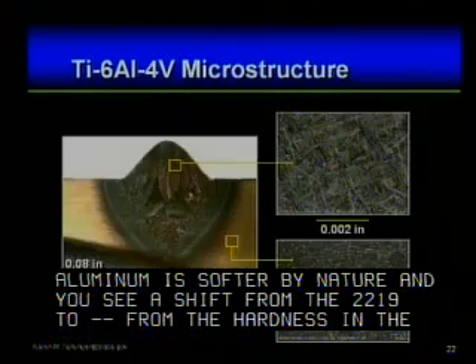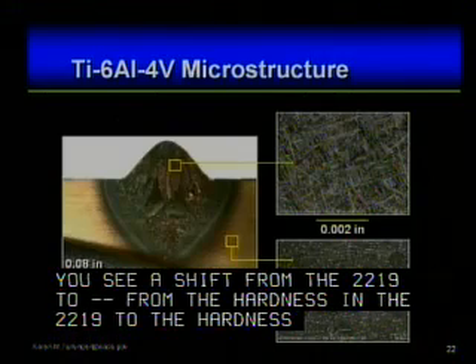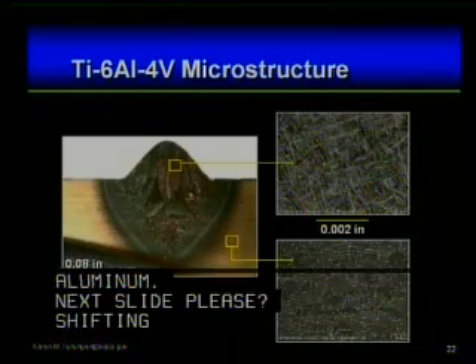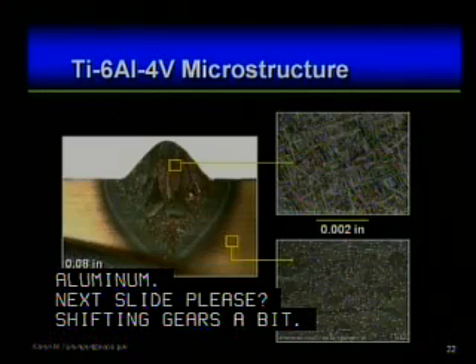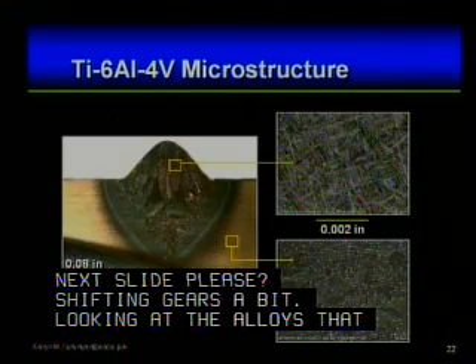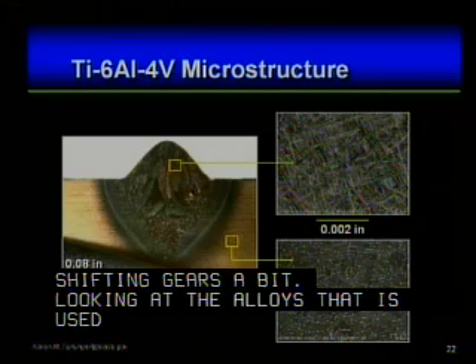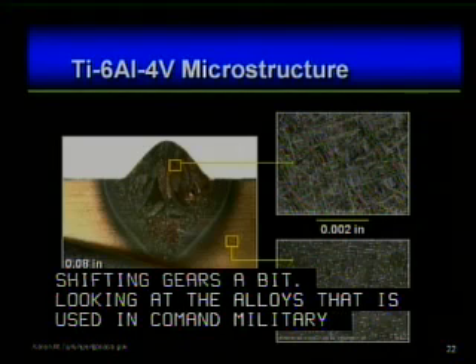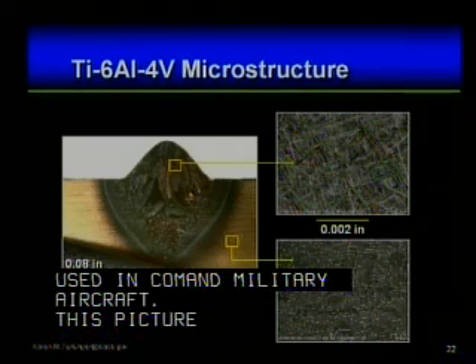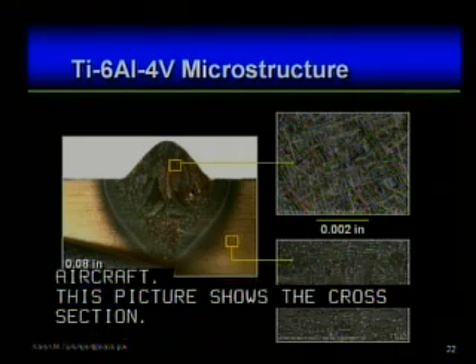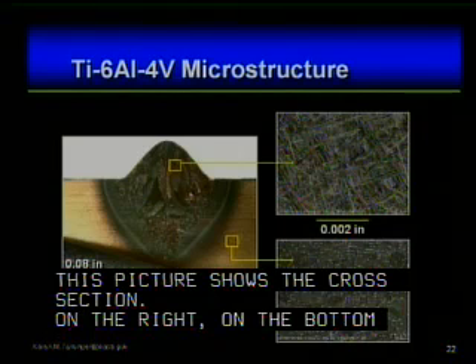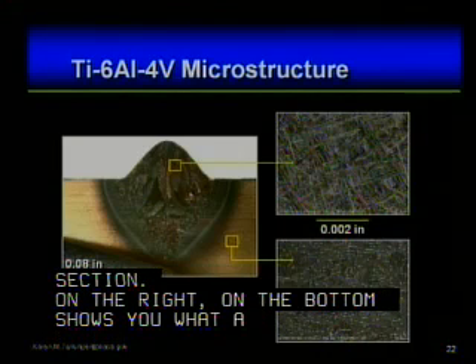Next slide, please. Shifting gears a little bit, looking at the Ti-6-4. Again, this is one of the alloys that's very heavily used in both commercial and military aircraft. This picture shows on the left a cross-section of a single bead deposit. The picture on the right on the bottom shows what your typical plate microstructure would look like, and you see a similar microstructure to what we saw in the aluminum.